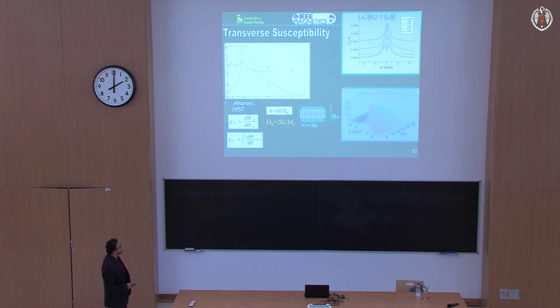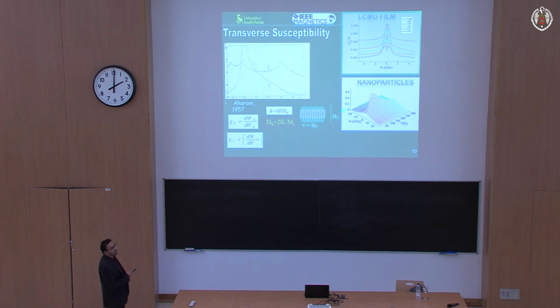For nanoparticles, for example, these are 10 nanometer maghemite particles, gamma Fe2O3. This is to show you that we can do this experiment very quickly in a PPMS. We can change the temperature and the DC field, and we can get some kind of a phase diagram, if you may, in the HT plane of how the magnetization dynamics changes, okay? For example, you can see the superparamagnetic behavior, that's 1/T dependence, blocking here, and then you can actually see the peaks here. So we can characterize everything using this experiment. It's a very powerful technique to probe the effective anisotropy, all right?